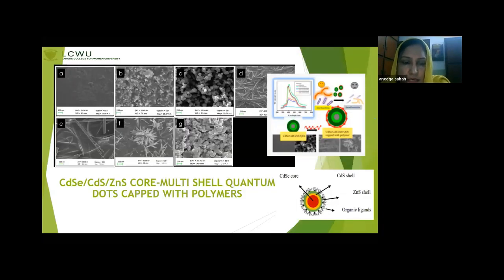This is the approach of multi-shell quantum dots capped with polymer, with cadmium selenide, cadmium sulfide, and zinc sulfide core materials, and we got very good results.